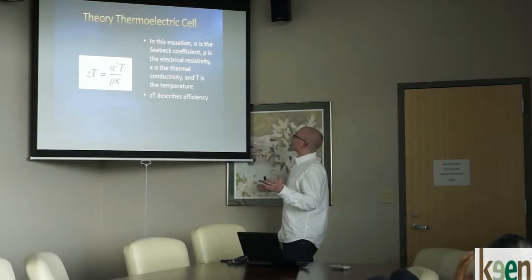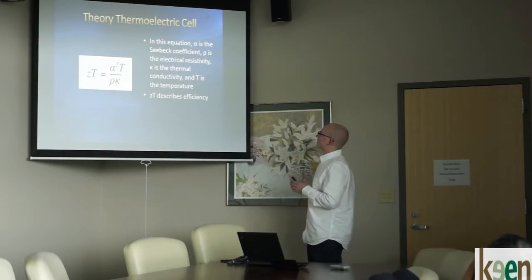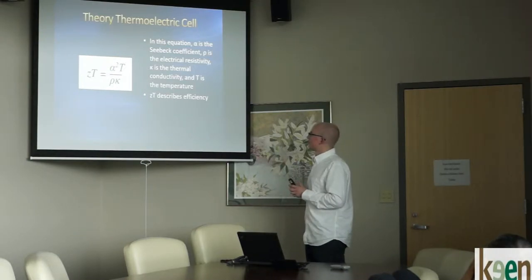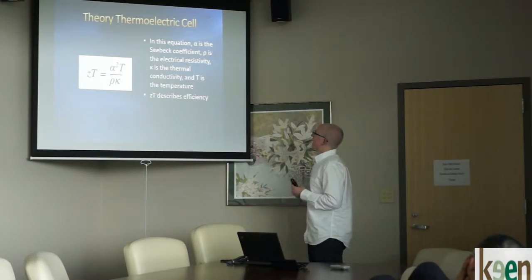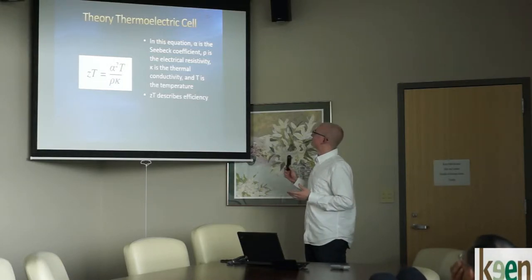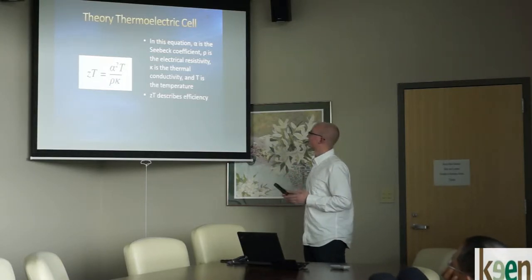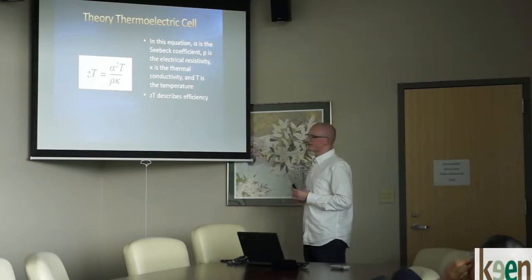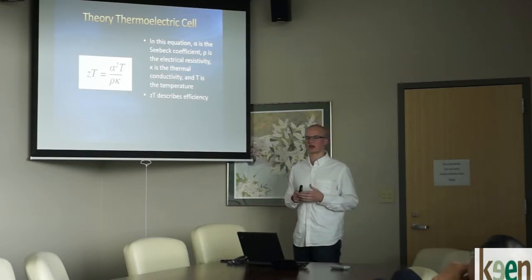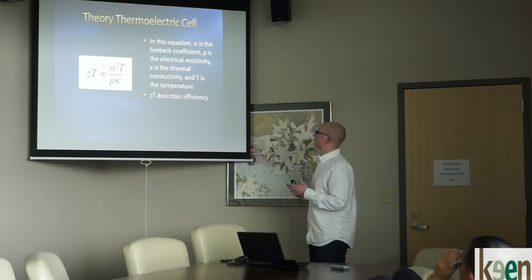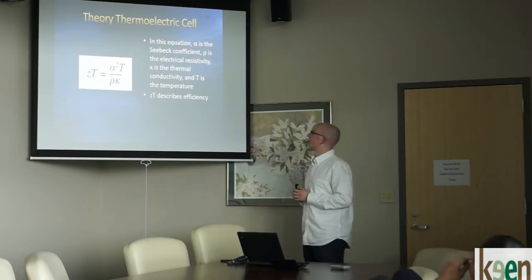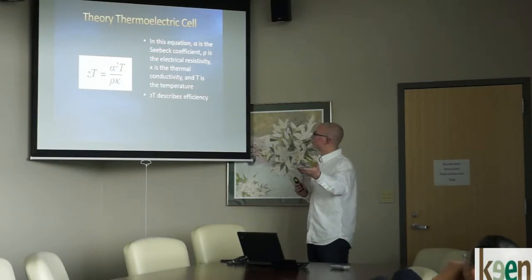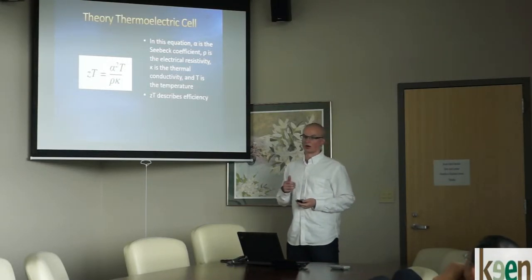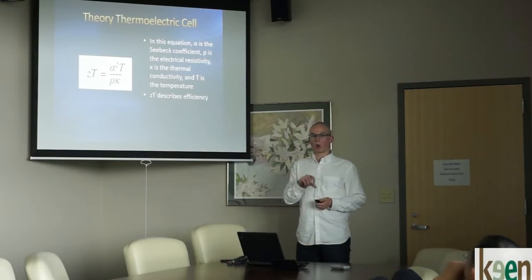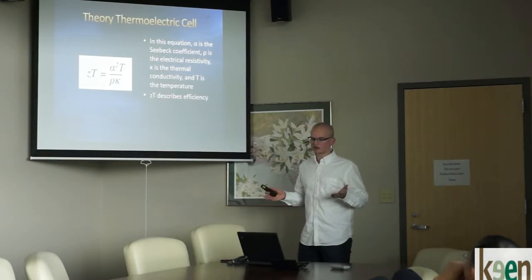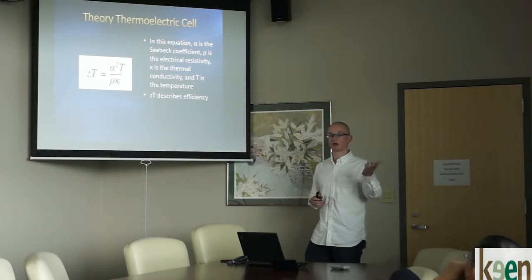This is the theory for the thermoelectric cell. This is the equation that describes the efficiency of the cell. Alpha is the Seebeck coefficient, rho is the electrical resistivity, k is the thermal conductivity, and T is the temperature. This is the equation that, up to present day, has driven how we look at building these thermoelectric cells. This is what has moved us towards semiconductors, because they are great electrical conductors, poor thermal conductors, and generally have higher Seebeck coefficients than pure metals or alloys of metals.